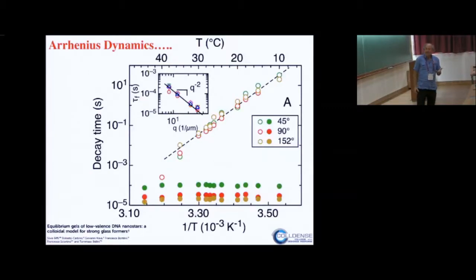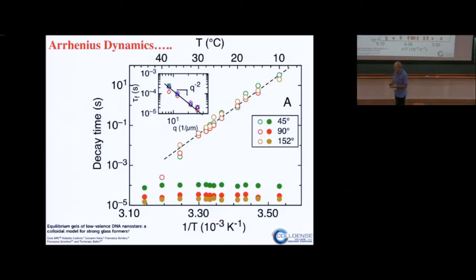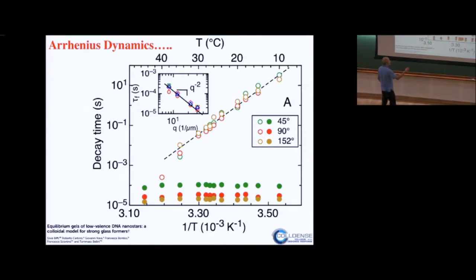There is a lot of interesting physics that we've seen with this system. First of all, this is a network, right? And networks, we know that they are strong glass formers. So the typical correlation time grows in an Arrhenius way. And here is the alpha relaxation time, plotted as a function of 1/T. You see how nicely it behaves. So this is, if you like, a colloidal analog of a strong glass former.